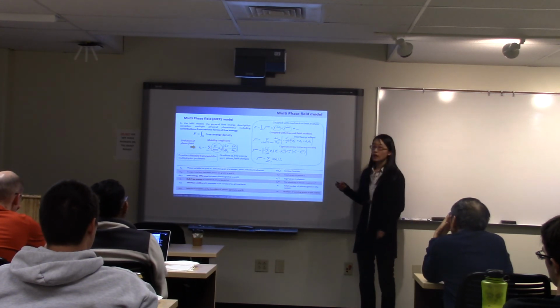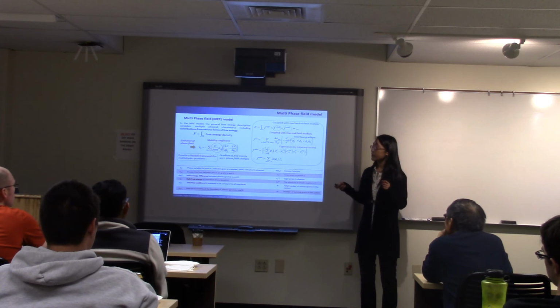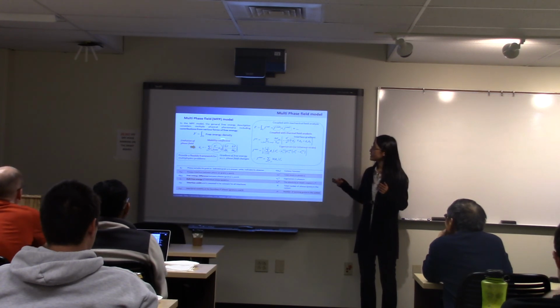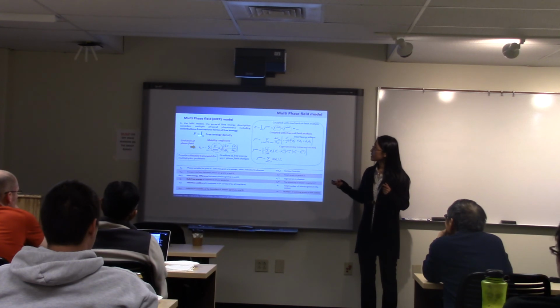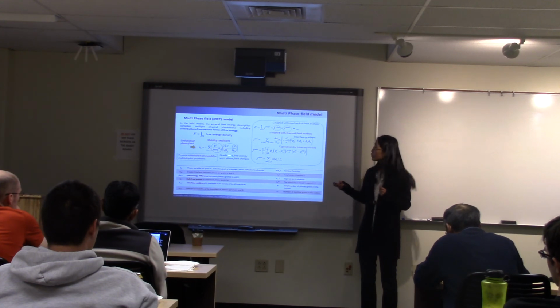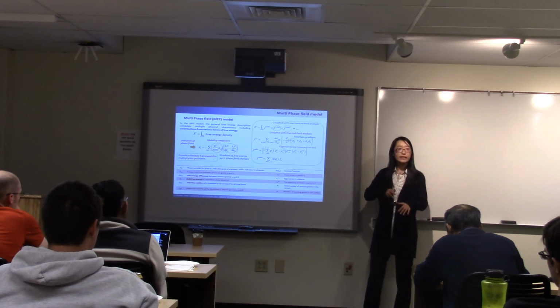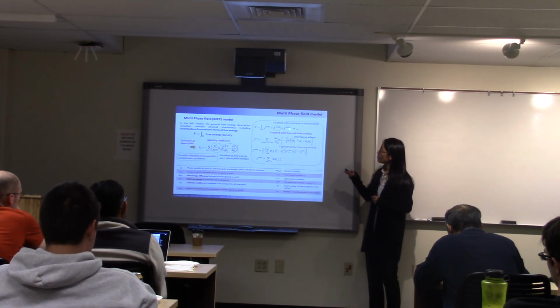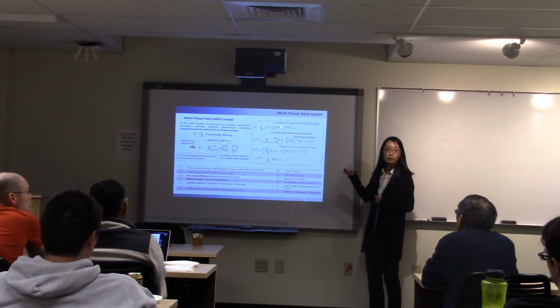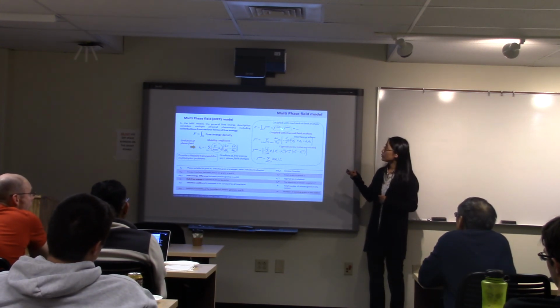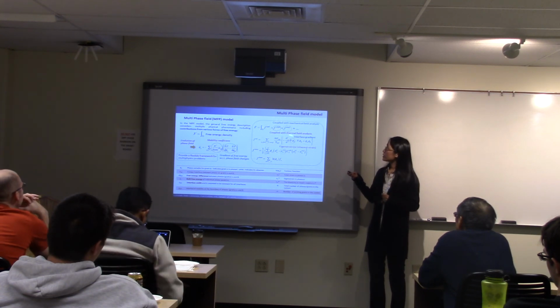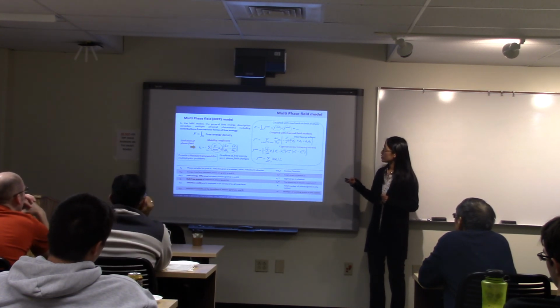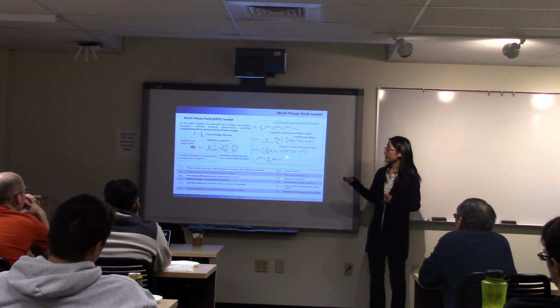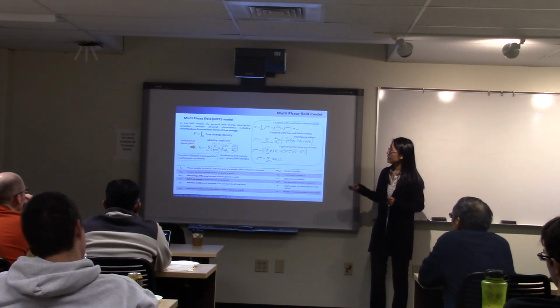And so first we need to construct the free energy expression with contributions from the various forms of the free energy density. And then after we have this, the evolution of the phase field can be predicted using the Allen-Cahn equation, which is the gradient of the free energy. And this phase field can be easily coupled with other field analyses. For example, it can couple with the mechanical field analysis through this elastic term, and couple with the thermal field analysis through this chemical term, with their detailed free energy expressions listed here.